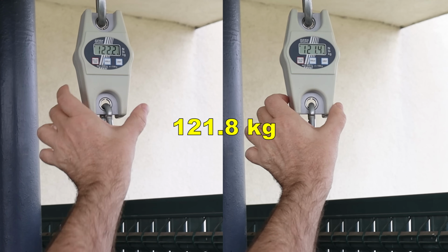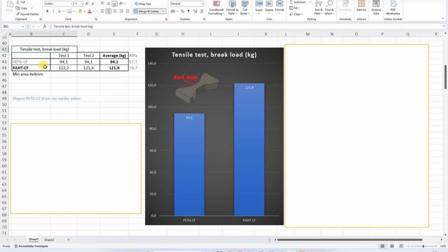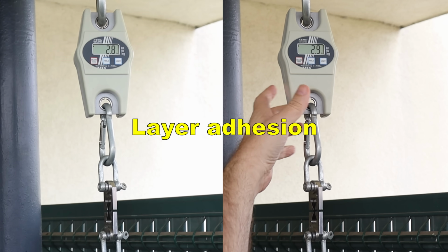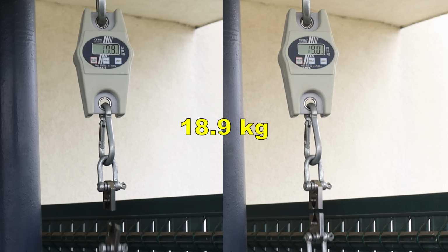Tensile test with horizontally printed test objects. Very strong. The results, and for better reference, I will include here the data for Elegoo PETG-CF from my earlier video, and we can see that PAHT-CF is significantly stronger than PETG, but overall this is a very strong material in this test.